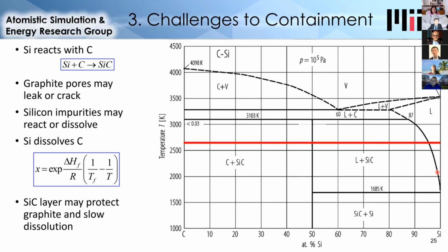And so that means in the cold tank, 1% of carbon could dissolve, but then when the silicon is pumped into the hot tank, another 4% could dissolve. But then when the silicon is pumped back to the cold tank, the excess carbon could precipitate out of the liquid and deposit in the cold tank. And so this cycle could cause material loss from the hotter sections of the system. Now, this could obviously be a problem.